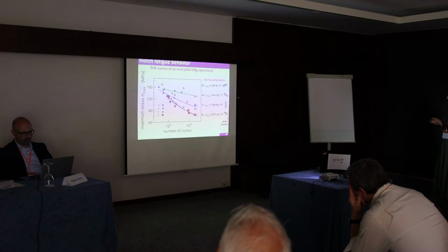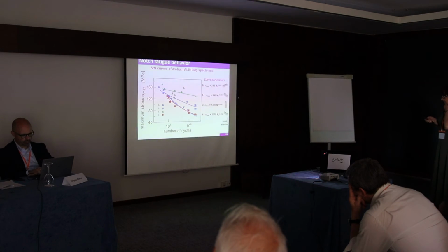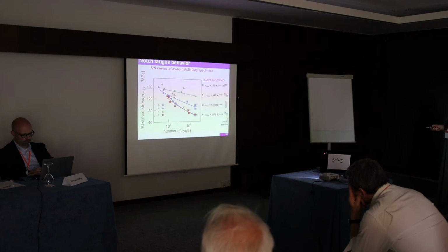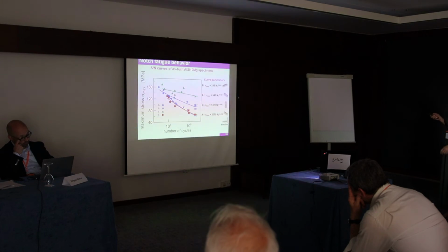So here we can see some curves of as-built AlSi10Mg specimens, and from this we can see that the best behavior has the orientation B, then A plus and A minus are lower, then these are also comparable to the direction C, and from this we can see that A minus has the worst properties, the worst fatigue life.